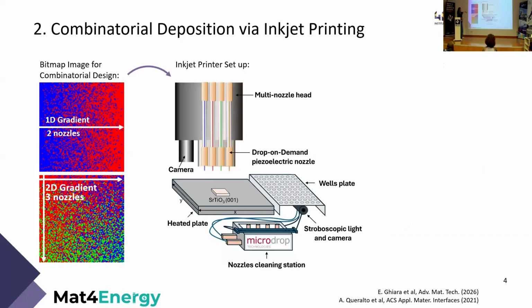So this is what we give to the printer. And so the idea is we can only eject 1 drop per location, because otherwise we would not have homogeneous thickness of the layer. So we cannot print 2 drops in the same place. But we still want a linear gradient in rare earth composition. So we achieve that by diffusion. And even by TEM, we prove that the diffusion is really good. I mean, there is no cluster of one rare earth compared to the other.